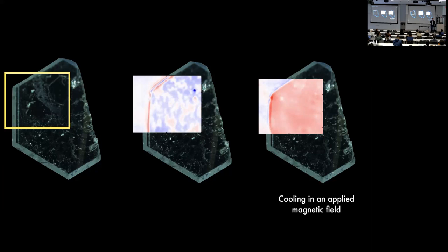And that is actually a pretty deep idea. You've got a broken symmetry. In this case, it's time reversal. And what you've put the system in is a time reversal symmetry breaking field, a magnetic field. In other words, you've externally broken the same symmetry as the order parameter. And by doing that, you've basically coupled directly to that order parameter and told it which direction you want it to go. And this idea is strongly generalizable.